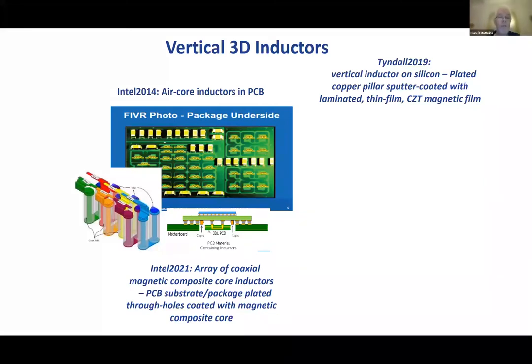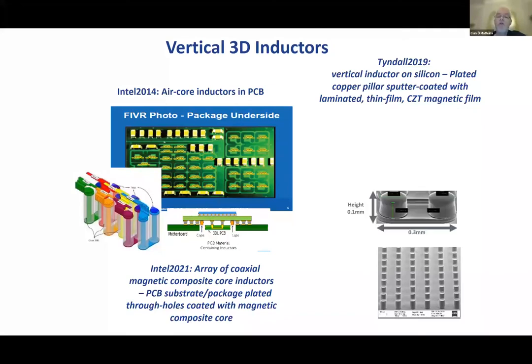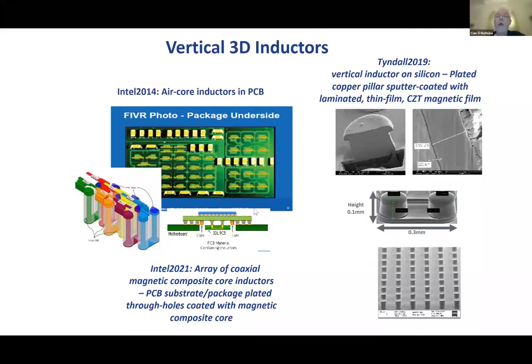So they've used the printed circuit board concept. And what's really interesting is we have completed a project this year, which was funded by Science Foundation Ireland, to do something similar, but actually do it in our silicon fab with our thin film materials that we have been using. So here you have a copper pillar, two copper pillars, and then we have deposited the magnetic material around those copper pillars. So you can get an array of these inductors taking up a very, very small space.